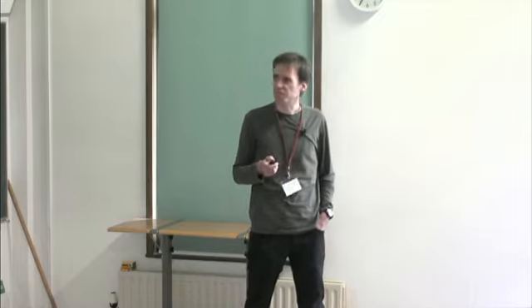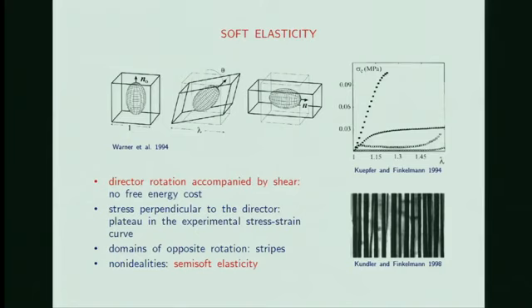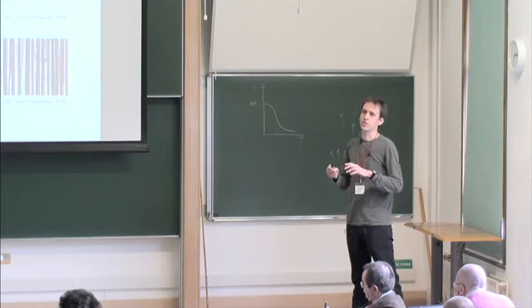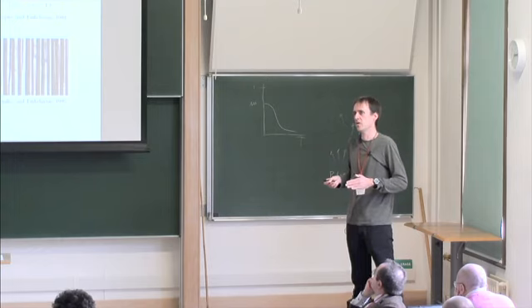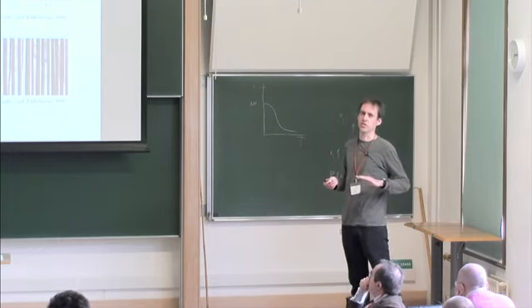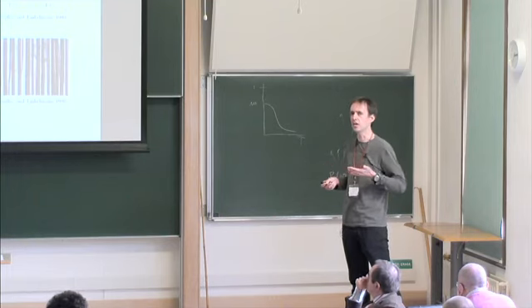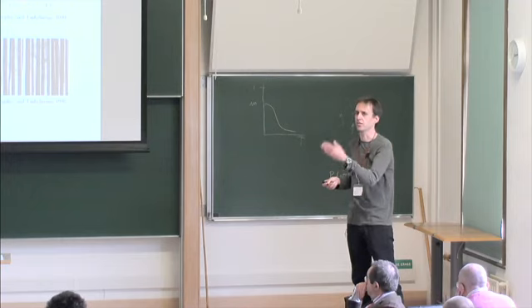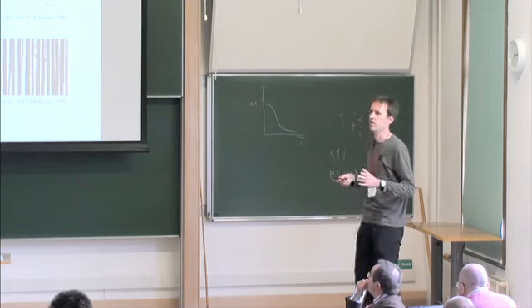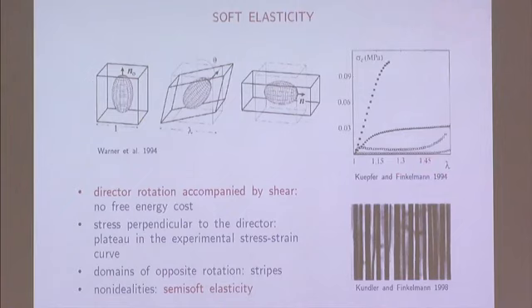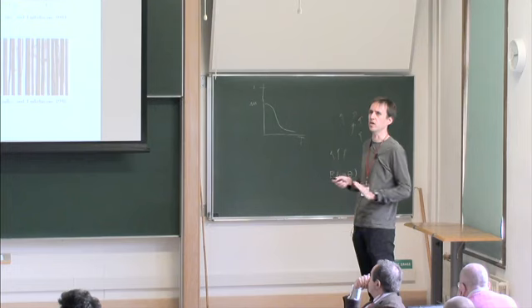Okay. Now, however, there's an even more striking phenomenon in liquid crystal elastomers. It's called soft elasticity. For example, if one had a monomeric liquid crystal, starting from the isotropic phase, you cool down your system, you will have your nematic director established along one direction. All of the directions are kind of equivalent if you have no external confinement or an external field. And then in between these equivalent orientations, one can rotate the director at zero free energy cost.